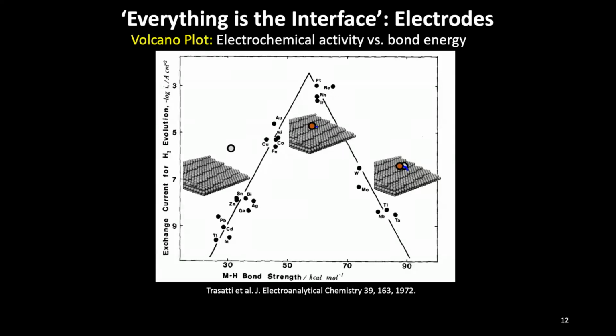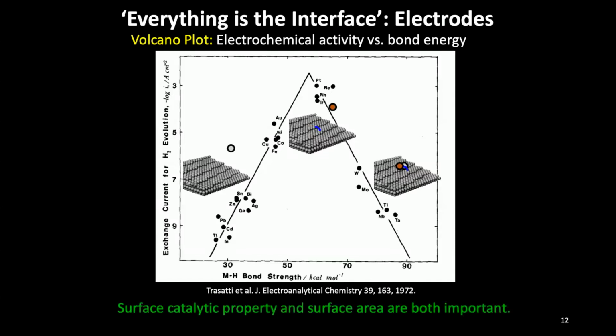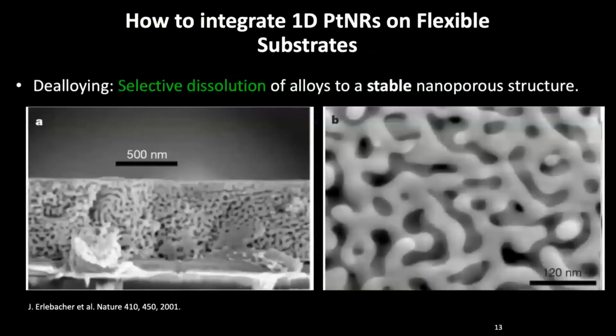So you just need a metal with the right metal to ion energy so that the ion can come in, participate in the Faradaic reaction, and clear the adsorption site for other ions to come in and again repeat the process. And that's why platinum is the most efficient catalytic material, because of its suitable metal to ion bond that allows it to have a lot of these Faradaic reactions without blocking the adsorption sites.